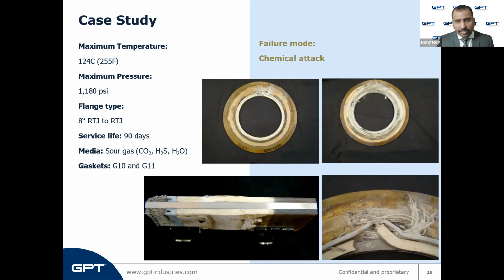The cause of failure was a combination of attack by sour gas and the effects of steam hydrolysis. You can see from the images that the inside of the gaskets were devoid of epoxy, extending all the way through, well, approximately 66% of the gasket.